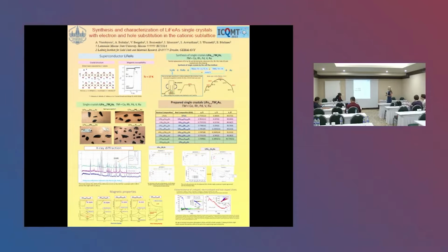On this slide I present my work about the synthesis and characterization of lithium iron arsenide single crystals with electron and hole substitution in the cationic sublattice. Lithium iron arsenide has the crystal structure shown in this picture. There are iron arsenide layers separated from each other by lithium cations, and it is known to be a superconductor with Tc of about 17 Kelvin.